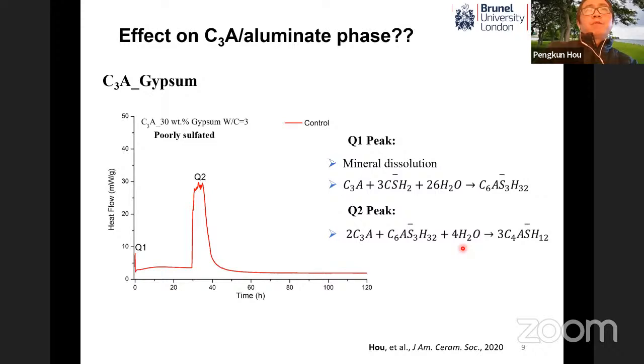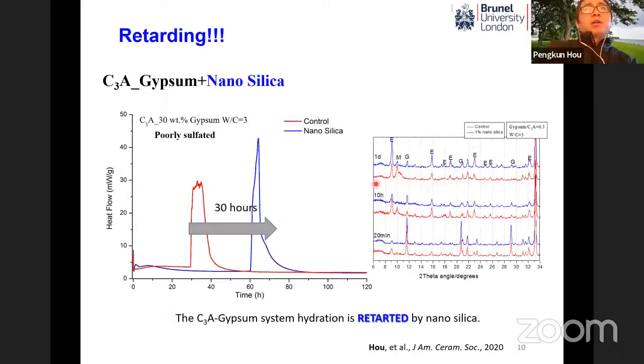So what will be the effect after addition of nanosilica? It's astonishing to see that the addition of nanoparticles retards the hydration of the aluminate phase. And this retardation can be confirmed by the phase assemblage transformation, I mean, the formation of ettringite or the transformation to AFm.